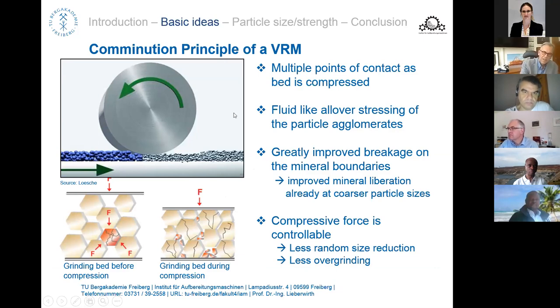Coming to the principle of confined bed comminution, essentially we see here the material consists of a number of layers. According to Schönert, it should be at least 5 to 6 times the diameter of the maximum particle. And you have the so-called hydrostatic state of comminution, which means all particles are stressed the same way. And preferably, talking about selective comminution, if desired, we see that the weaker particles are breaking earlier than the stronger particles. And then, if that works nicely, according to theory, you just could use screening or air separation to get the finer particles out, and you get a pre-concentrate. So much about the theory. So you have multiple contact points, you have the fluid-like all-over stressing of the particles, and you have less overgrinding in the material.